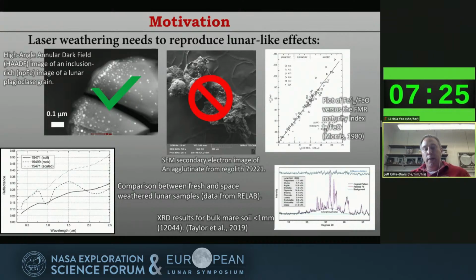But in measuring Is/FeO of our short pulse laser space weathered regolith, we don't get very high in Is/FeO. We only get about 10 or 14, which is very immature. So we don't replicate that feature very well. In the case of spectra, we do that pretty well.